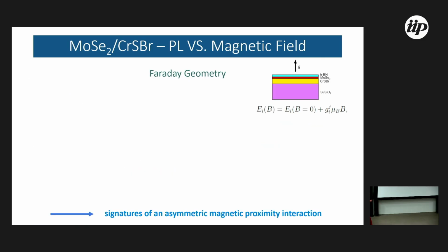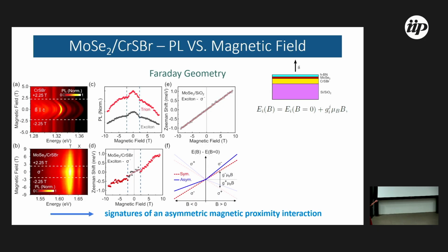This is the message. But it's more complicated when you apply a perpendicular magnetic field, because we have this effect that I showed, but also a change of the valley properties. You have this correlation with the phase transition here, but if you measure the Zeeman shift, I can extract the valley g-factors, and they are asymmetric. This is evidence that we have signatures of proximity effect.